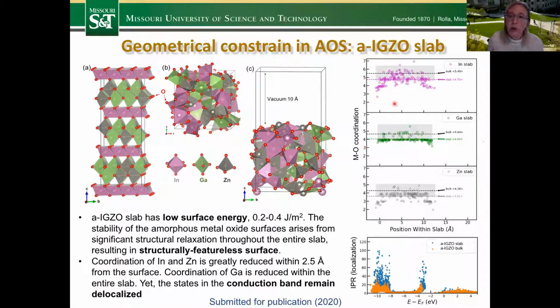So for all atoms, not only indium and zinc, show significantly lower coordination, but also for gallium, the average is actually significantly low throughout the entire slab. So the geometry really affects this coordination significantly, yet the states in the conduction band remain delocalized. That was a very interesting fact that we found, that the conduction band is still delocalized. We don't see strong localization unless we go to highly non-stoichiometric material for these oxides. Tail states in the valence band, of course, increase.